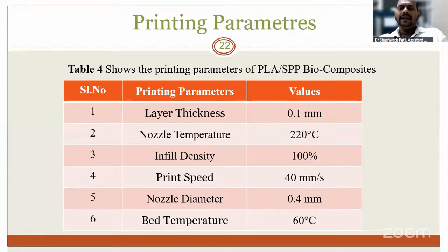Then what are the print parameters? As you can see, for our study of the composite filaments, we have used a layer thickness of 0.1 mm, a nozzle temperature of 220 degrees, and an infill density of 100%. We have given the 100% infill density to strengthen the material, with a print speed of 40 mm/s, a nozzle diameter of 0.4 mm for the print, and the bed temperature kept at 60 degrees.